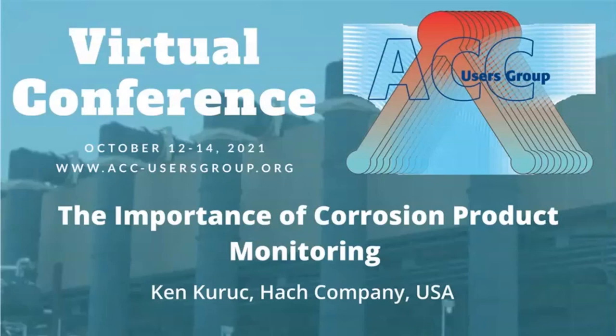Okay. I heard a couple of questions on the chemistry, and there are a couple of different chemistries she's using. As Shana mentioned, one of the products she's been using for a while is a concentrated product. It's basically OLDA, with a little bit of OLA in there as well, but largely OLDA, and the product with a tiny bit of MEA as well. Now, the next chemistry, the Polyamine Plus, I heard a couple of questions there. That is a filmer-only product. And it is, as Shana pointed out, contains an amine and non-amine secondary surface active chemistry as well.